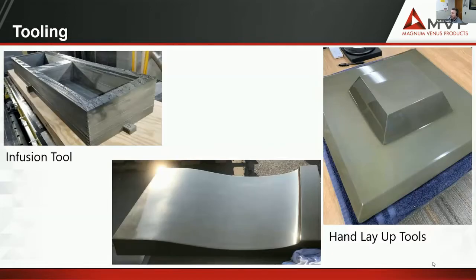Some other tools that we've done: that was the marine tool that you saw that we printed. It was over 1,000 pounds. That was an infusion tool. The tool on the far right was just a hand layup tool that we did for a composite shop. And the tool in the middle was a vacuum tool that we're using for pre-pregs. That's a 2-piece mold that was flipped over to match the other mold, almost identical to it, that they put a bladder in the inside of, and they pulled, and they're doing a pre-preg on it.